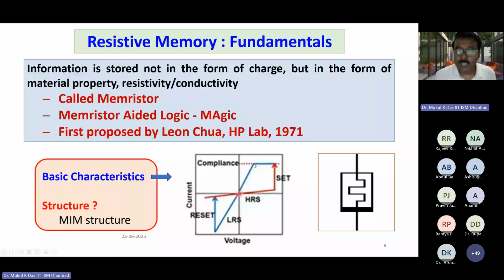Now gradually, the films that were formed are vanishing. One by one, the vacancies, like oxygen vacancies, are being distributed throughout the device. So the resistance increases. That means current decreases. And the current decreases following this path almost linearly, and it comes down to zero at again 0 volt. If it is not 0 volt, if some initial things are there, then at 0 volt while retracing you may not get the zero current. Due to some inertia, some film formation may be there.